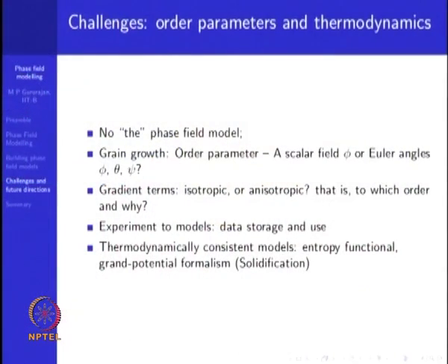Of course, there is also the question of thermodynamic consistency. In the case of solid-solid phase transformations, we demand free energy and its minimization. In cases like solidification, where temperature is not a constant, one may have to look at entropy functionals, and there are formulations like the grand potential formalism, which becomes important in such cases. So, these are some of the challenges associated with order parameters and thermodynamics.